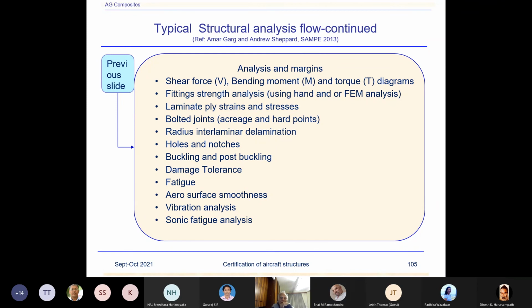Well, you have to analyze the hole. Suppose it's a 6-inch hole. You have to consider that damage, like a notch, like a 10-inch crack in the stiffened panel. You have to analyze that, and it has a lot of issues. In fact, they are not easy to analyze. The methods have been developed, especially for stiffened structure.